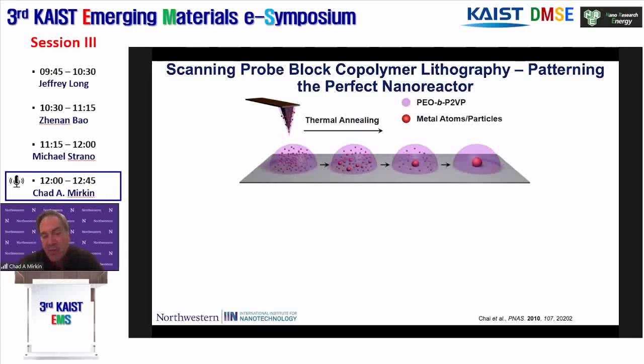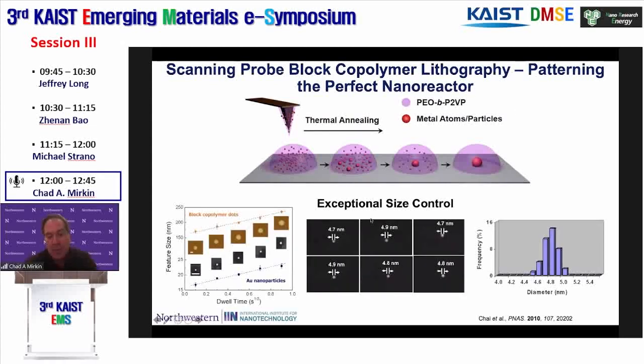The importance of that is the volume of that reactor is very, very tiny. It's attoliters to yoctoliters in volume. And then we process the reactor and heat under reducing conditions so that we reduce the metal atoms, cause them to coalesce, and then eventually blow away the polymer, so at high temperature. And we'll talk about temperatures from 600 to 1,000 degrees in certain cases. And this is kind of interesting because the reactor in this case is both the solvent and the physical confinement vessel. And the reaction is a reaction where all of the reactants, at least as I've described in cartoon fashion, go to one single product. And that's really important in terms of control. How do we know that's the case?